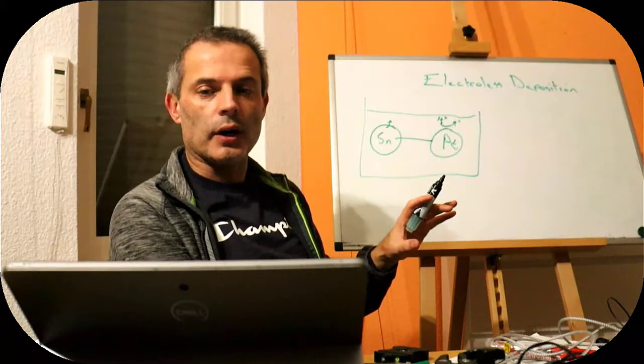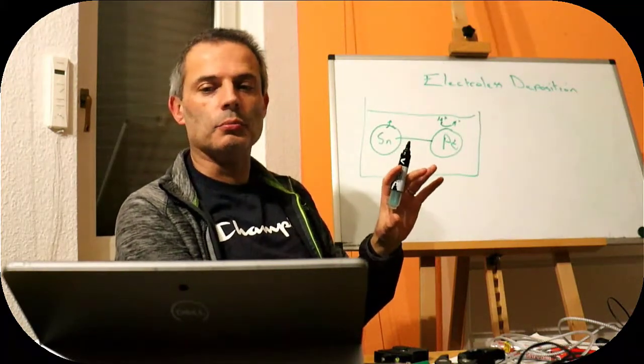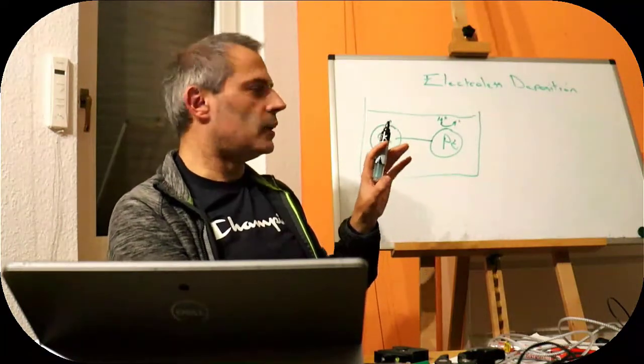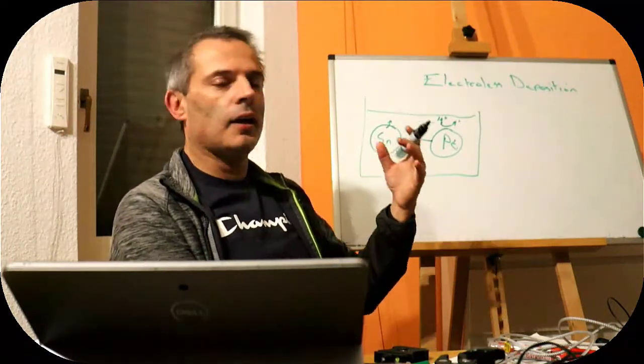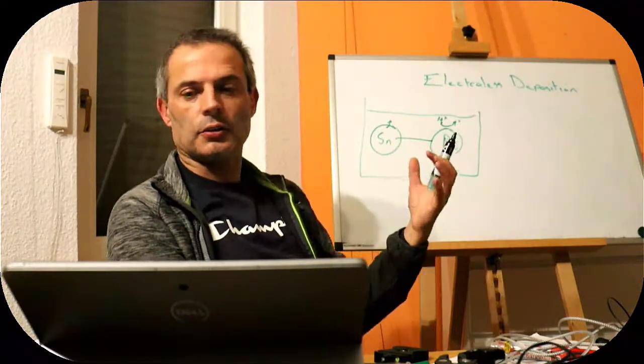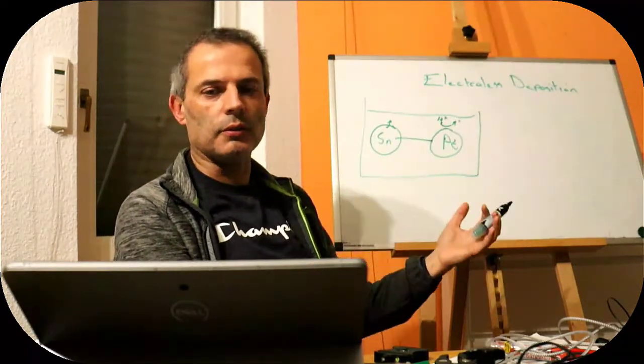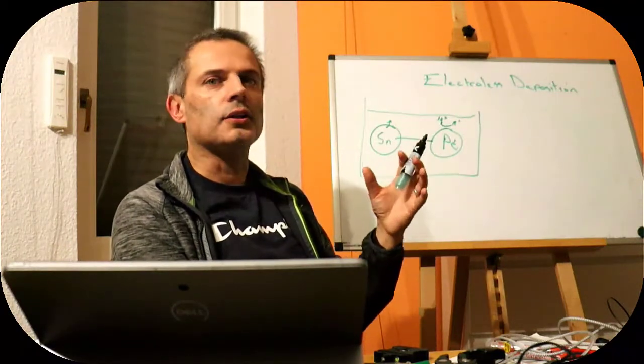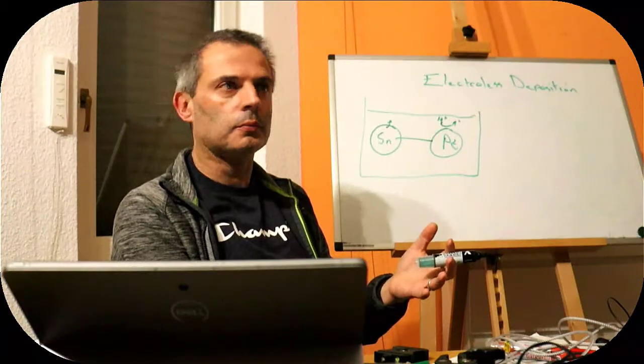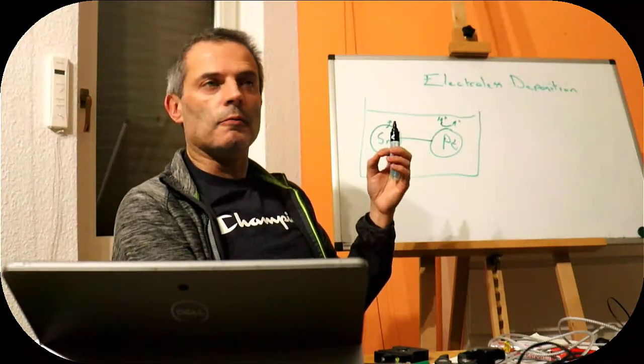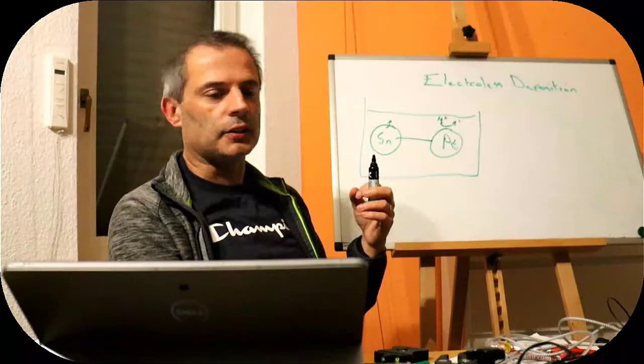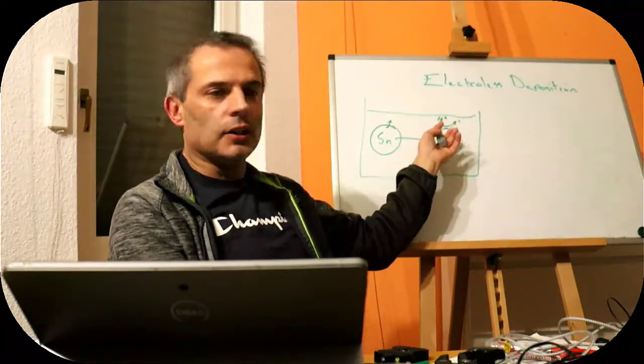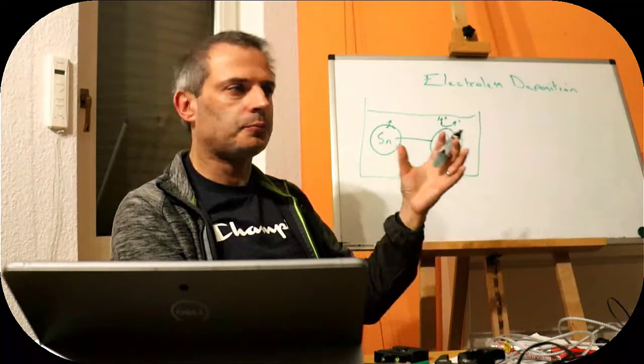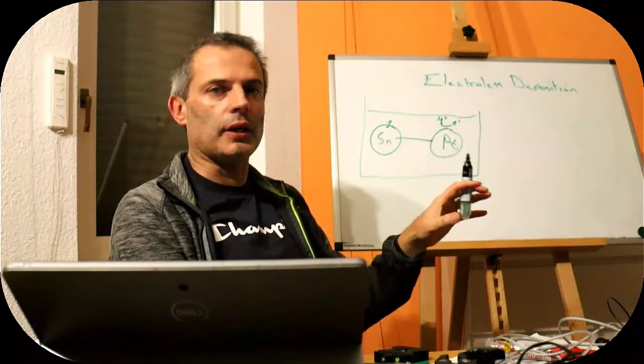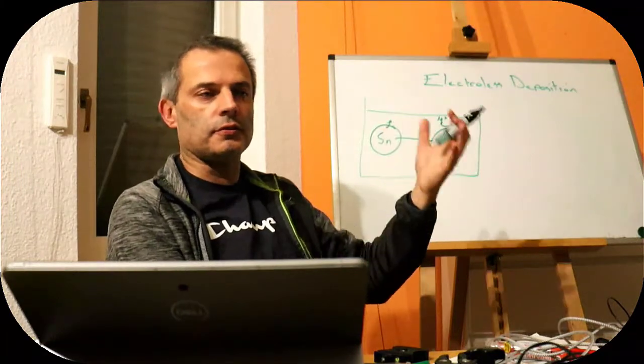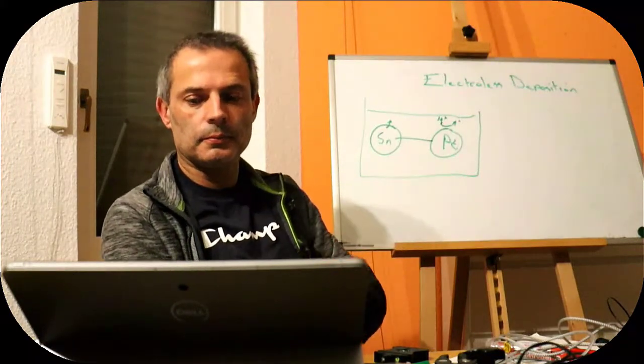So now we have a way to see why our reaction might not happen or might be located in a place that we want to. In solution, it's very difficult sometimes for reactions to happen, particularly redox reactions, but also other types of reactions, and so they go comparatively slowly or not at all. They can then work far better on a conducting surface, because then the reduction reaction and the oxidation reaction don't have to take place at exactly the same place on the surface. Conduction along the surface is fine, so we can do it in 2 places.